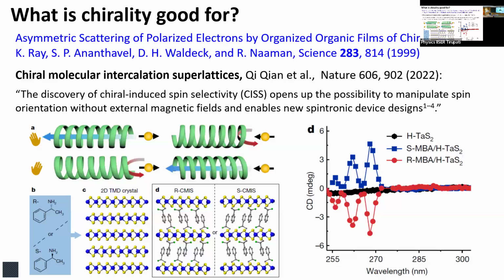So we are plotting the difference here, which is called the CD, as a function of the photon energy that I come in with left and right circularly polarized light, and the difference is what I am plotting. You can see there is no chirality in the electronic states here in energy, but there's a lot of chirality here because it's non-zero. If I have only tantalum, that's zero everywhere. But here it becomes chiral. If I reverse the molecule, this signal reverses itself, showing the system is chiral.